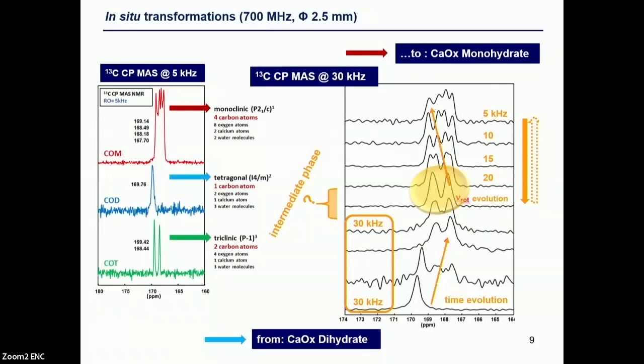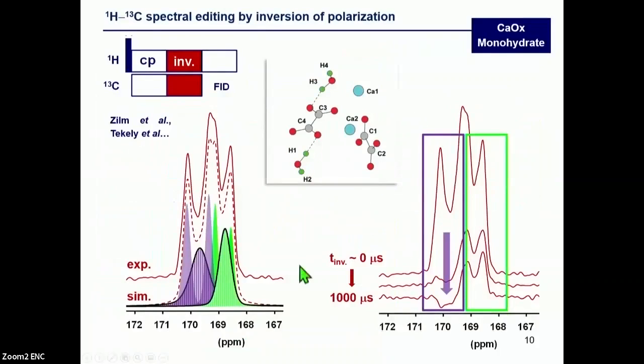So, in fact, if you go back to the spectrum corresponding to the monohydrate phase at low spinning speed, let's say 5 kilohertz, you always have to consider the combination of the first phase with sharp peaks superimposed to a second phase characterized by 2 broader peaks. And you see that probably these 2 broader peaks correspond to the intermediate phase we have discovered in the last slide. And in order to assign definitely the peaks, we decided to go to spectral editing by using the standard inversion of polarization experiment.